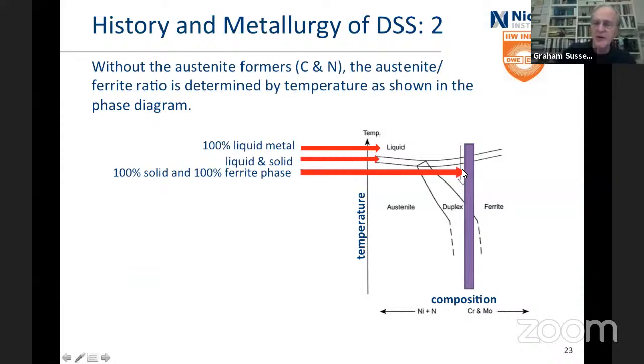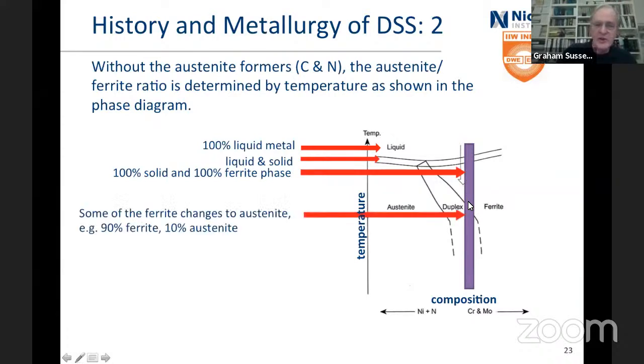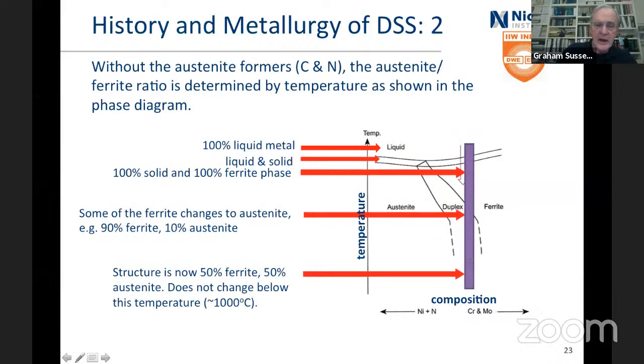And by the time it's solidified there, it's in the ferritic range and it's all ferrite. And it cools down to about 1000 degrees or so. And then you've got some of the ferrite going to austenite. And as you keep going down, it keeps on changing. And down there it gets to about 50% and 50%, and it doesn't change any longer because it's sitting at about 1000 degrees C at that point. And from there on, it's solid. So any change that's happening from there is going to be by solid state diffusion. And that's not fast. It definitely isn't fast.